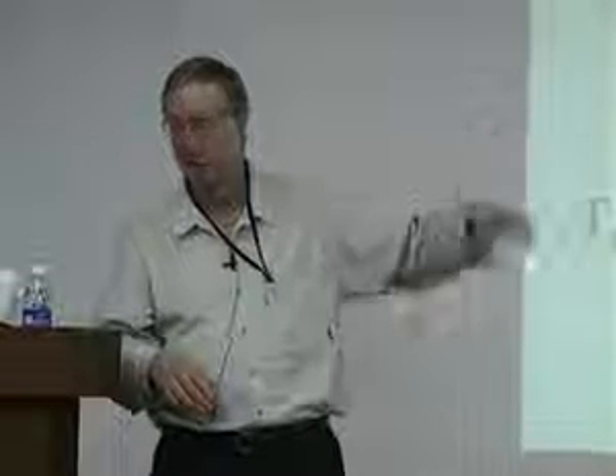And the apparent surface relaxation times in those instances are just too fast to be a glass. And they don't see any evidence of glassiness. They just see a fast relaxation, right? So from that perspective, it doesn't look like there's a true surface glass transition. It might be related to the surface being a very high fictive temperature. But even when they get down to pretty far below TG, a couple hundred degrees, they still see this rapid dynamics.